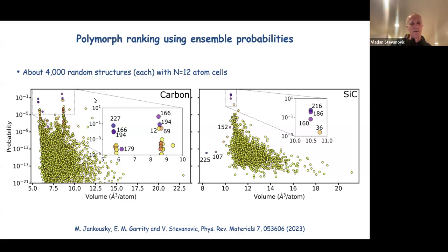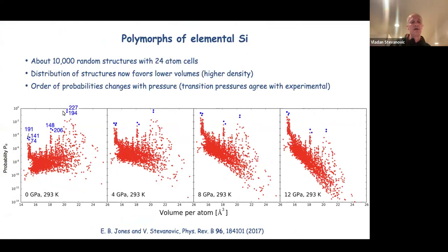Another question that may be interesting to discuss is that both of these probability distributions tilt to the right from essentially the diamond structure. So zinc blende is just diamond populated with two types of atoms. And there is a diamond structure here. So essentially the whole potential energy surface, as represented statistically by our random sampling, seems to be leaning toward less dense structures, or high volume structures. And one can then ask, is there any implicit bias in our random sampling? I will discuss that on yet another system, elemental silicon, which again has a diamond structure.